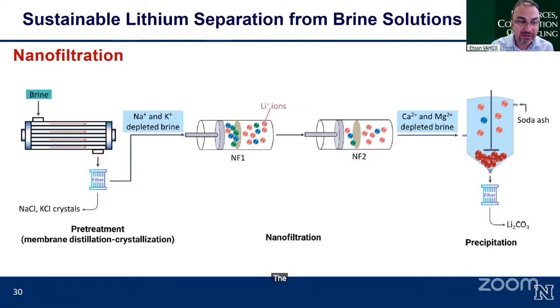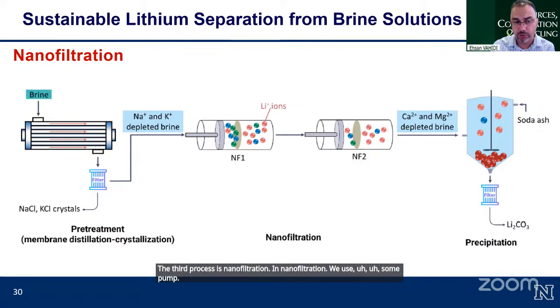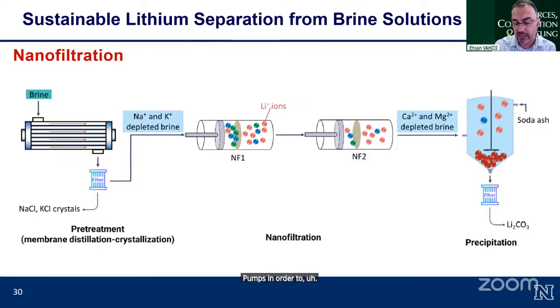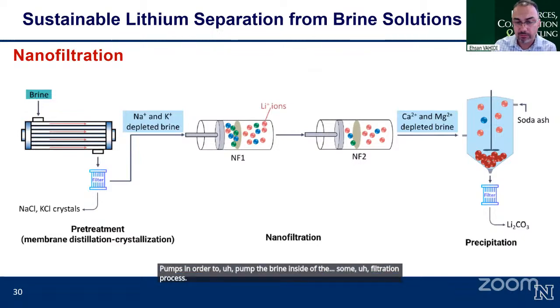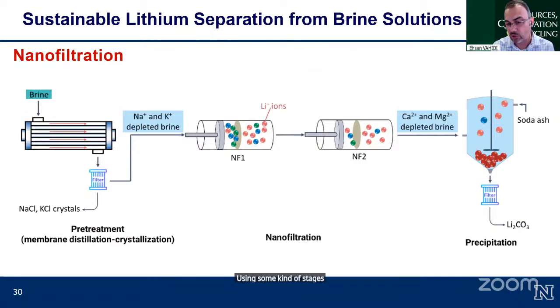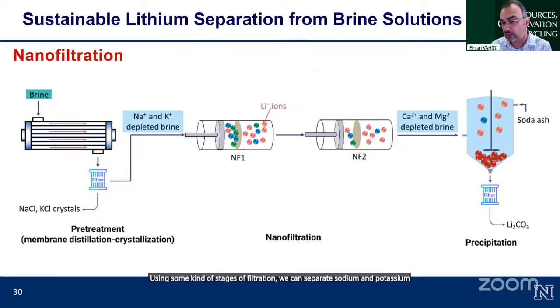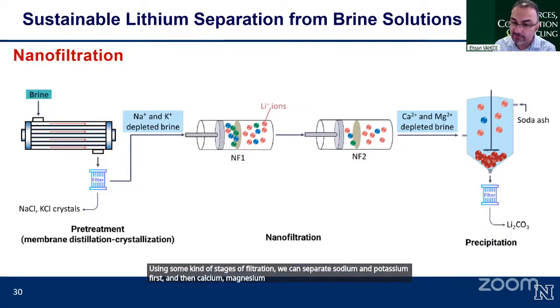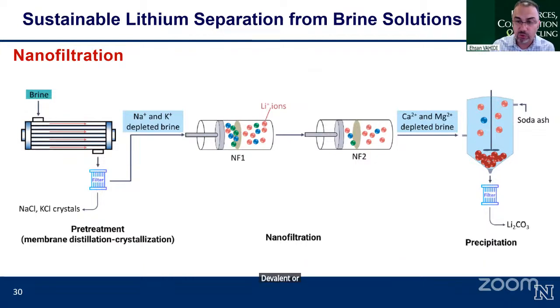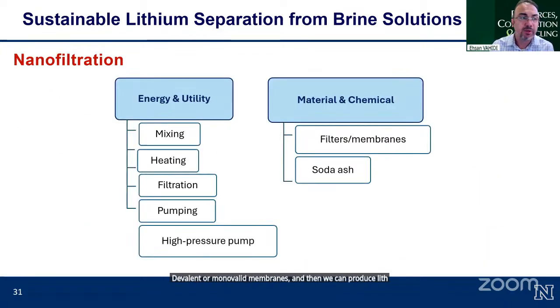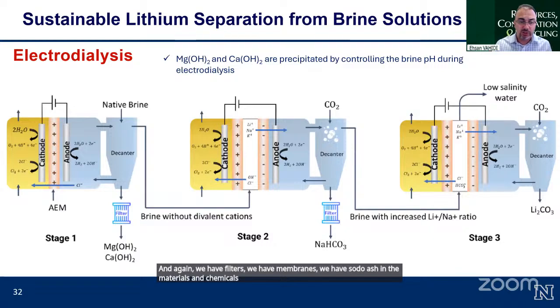The third process is nanofiltration. In nanofiltration, we use some pumps in order to pump the brine inside of some filtration process. Using stages of filtration, we can separate sodium and potassium first, and then calcium and magnesium, using divalent or monovalent membranes, and then we can produce lithium carbonate equivalent. Again, we have filters, we have membranes, and we have soda ash in the materials and chemicals. And the last process is electrodialysis.